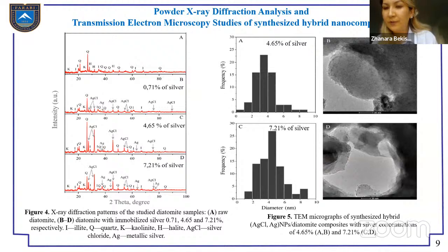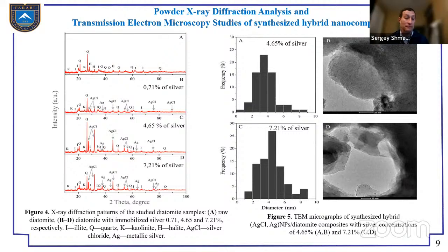I took them all from the microphotographs. So it was approximately 120, 115 nanoparticles. Okay, so I think the gold standard for statistical analysis of this type is at least 300 nanoparticles. But thinking of this in the bigger picture, there are millions and billions of nanoparticles, so you only take like 150 to determine the size of the sample. That's why it's also important to use other methods to validate your results, for example XRD analysis. Did you use any other methods to confirm your sizes? No, I didn't use XRD for confirming the size. Okay, it's good to know.